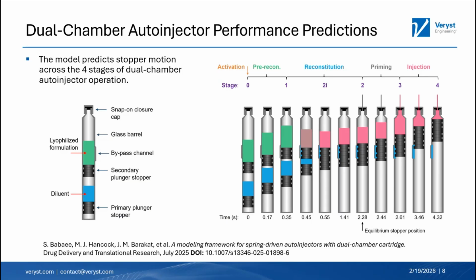Air pressure builds up in the drug chamber, balancing the spring force, and the stoppers come to equilibrium. Drug dissolution and mixing occur in a step that was not modeled, though later I'll discuss how we can use multiphysics simulation to address that step. Once the solution is mixed, the user activates the needle to pierce the seal in the closure cap, and this allows the trapped air in that second chamber to escape, and then the stoppers continue to move. The priming and injection steps follow after that. The model uses drug solution viscosity measured a priori, and it's provided as a model input. The model predicts both injection time and flow rate.